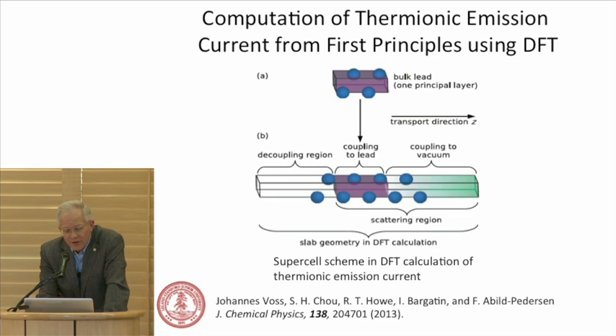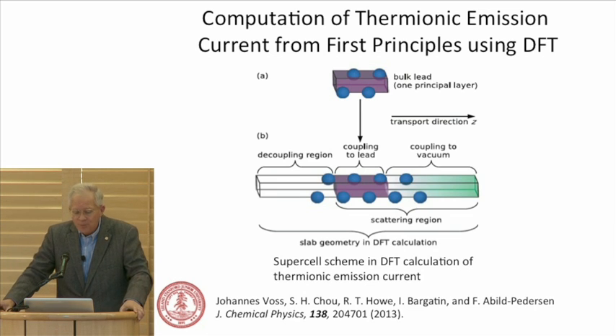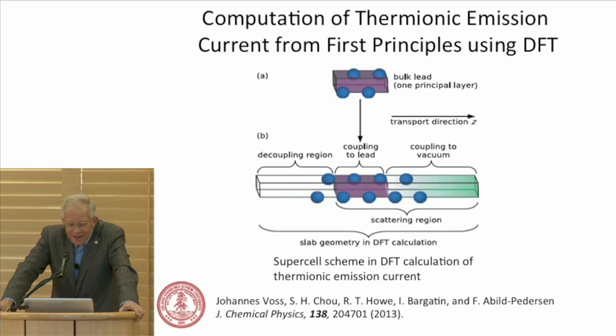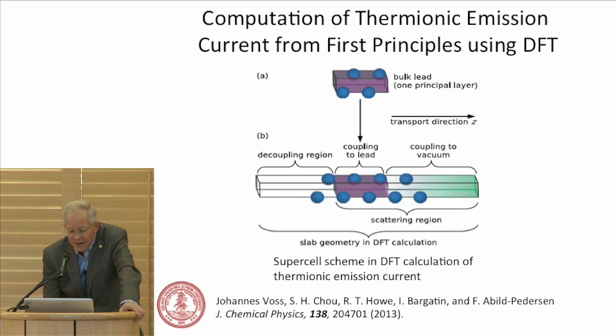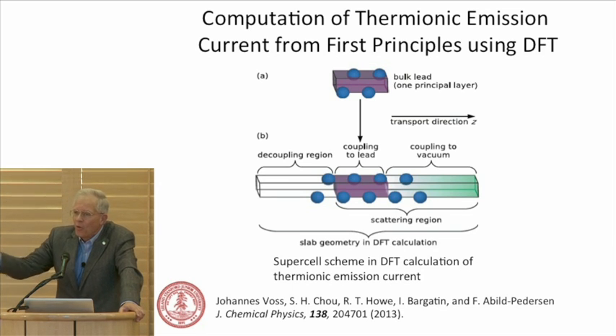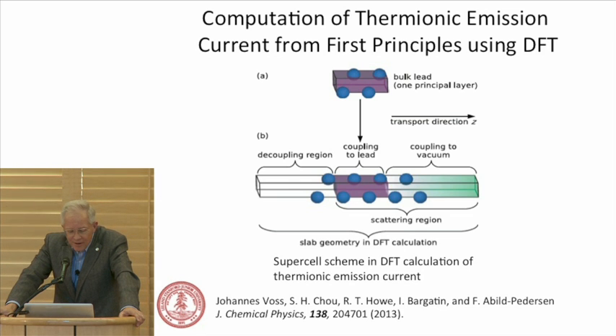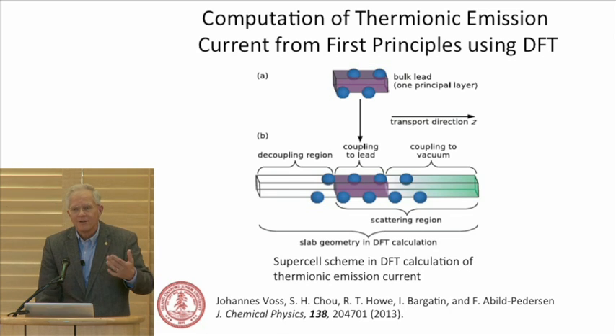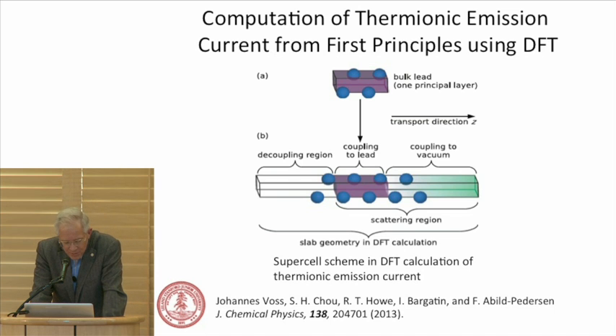Along the way, there were a lot of discussions on the inability to simulate the current density using density functional theory. Johannes Voss at SLAC and Frank Abild-Pedersen developed a way of extending the supercell into the vacuum and adding a decoupling region to the lead, to the interconnect, and essentially first-principles simulating the current and benchmarking that against experiment. So now we have the whole basic function of that high temperature material, work function and Richardson-Dushman coefficient, for the first time. Our ability is to simulate that, to compute before we do the fabrication.